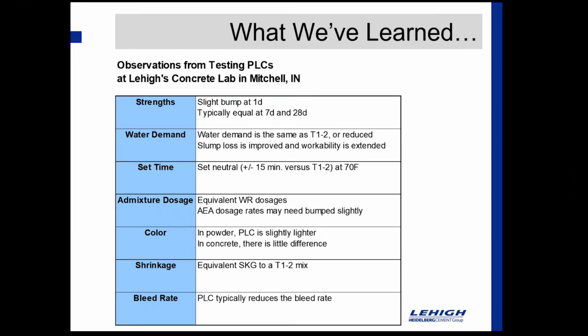Shrinkage has been nearly equal, dead on equal with the type 1-2 mix, and something that we found to be a potential benefit is the PLC typically reduces the overall bleed rate. Again, I think that's a function of that fineness that we see.